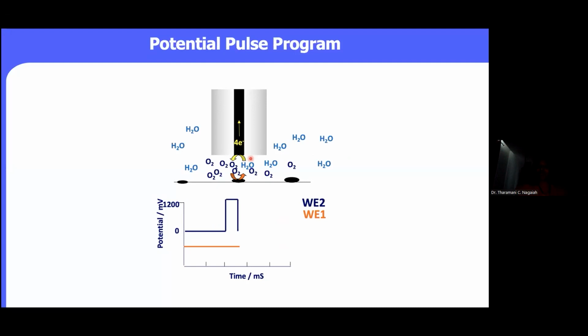Since it's a microelectrochemical approach and also the electrode is just placed 10 to 15 micrometer above the electrode surface, both the electrodes are competing for the available oxygen, and this we call local catalytic activity. In case you want to understand the oxygen reduction reaction, we need to purge the solution. But if we purge the solution, then we are going to create the convection effect. So to avoid this, we are generating the oxygen.